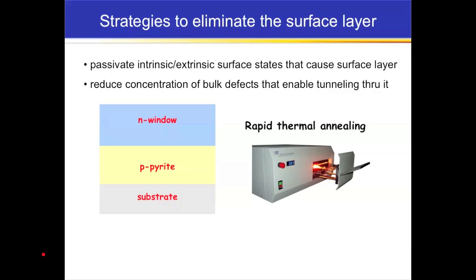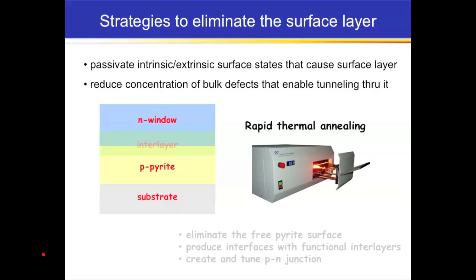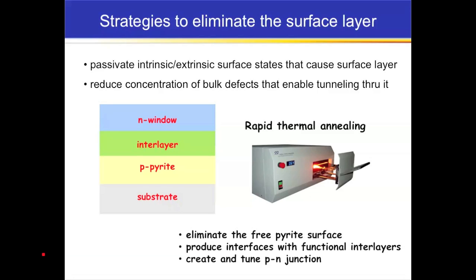Well, one way that we're approaching this is by taking pyrite that's nominally P-type, whether it's polycrystalline or single crystalline, it doesn't matter, deposit an N-type window layer on top of it, and then do controlled thermal annealing to try to get interdiffusion across this interface and essentially destroy the pyrite surface, or alter it so drastically that we remove whatever these defects are that are causing these pinning problems and the tunneling issues. So the idea is that we want to passivate the surface states, and we also want to reduce the concentration of the subsurface defects that might be acting as islands for trap-assisted hopping or trap-assisted tunneling. And so there's our interlayer formation, and we hope that by doing this, we can make more high-performance kind of PN junctions with pyrite.